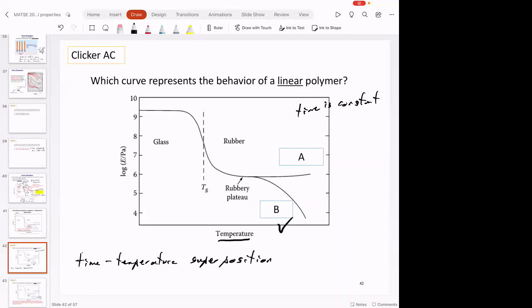If you take that ball of silly putty and put it in the oven, heat it up, and somehow keep it round, and then smash it with a hammer at high temperature, it won't shatter, or it won't shatter as much as it did at room temperature, because you're allowing those chains to relax faster at higher temperature, even though the time is the same. And so that's really interesting.